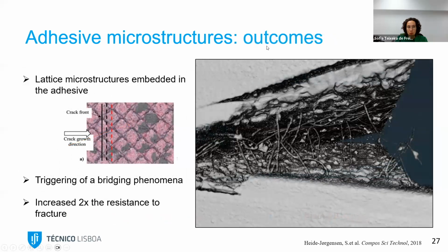So what we saw with these microstructures is that these lattice microstructures embedded in adhesive could trigger the bridging phenomena, and we could increase two times the resistance to fracture of the adhesive. So this is very promising.